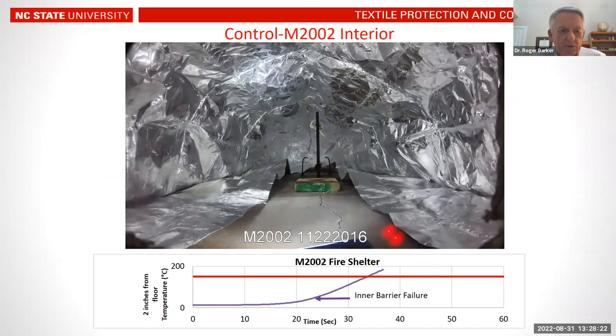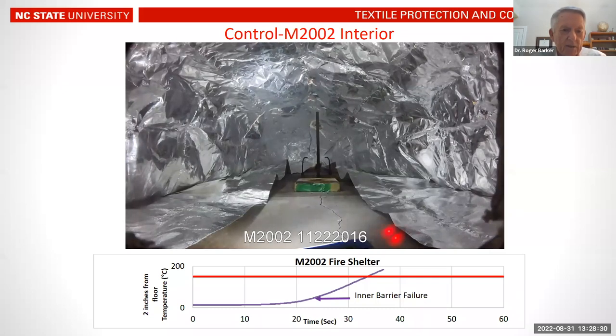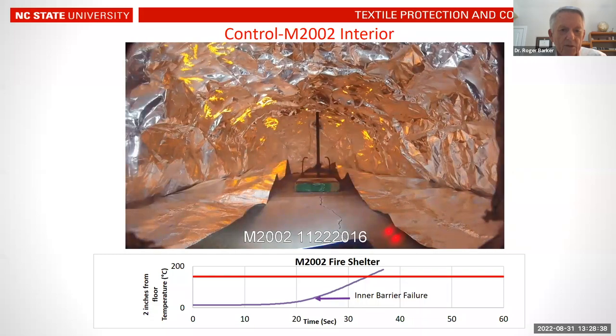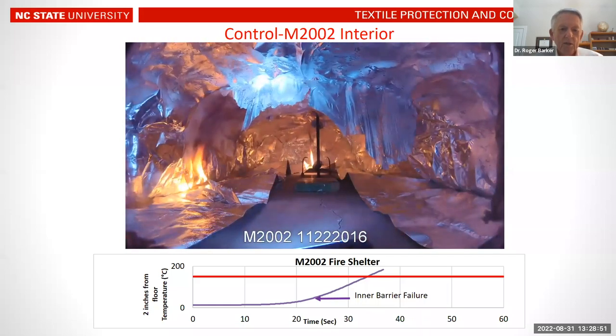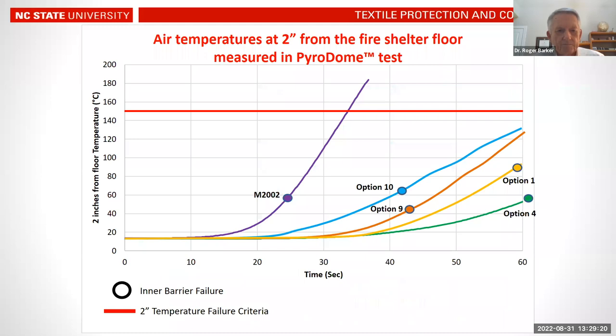From the inside view, you can see the shelter walls contracting as heat progresses, then emission from the interior layer, followed by full break-open and delamination. Obviously a person could not survive that situation. We took the time to reach complete destruction of the shelter material as an important metric, which usually occurred before the air temperature at two inches above the floor reached a non-survivable level — giving us two metrics for our lab studies.